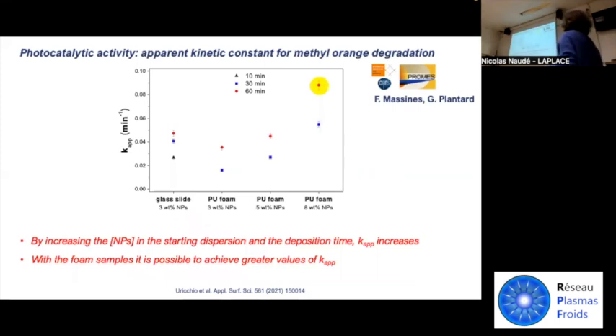And here, another view of the apparent kinetic constant for methyl orange degradation we obtained for our plasma coated glass slides and polyurethane foams is reported. Actually, the greater the apparent kinetic constant, the greater the photocatalytic activity of the material.